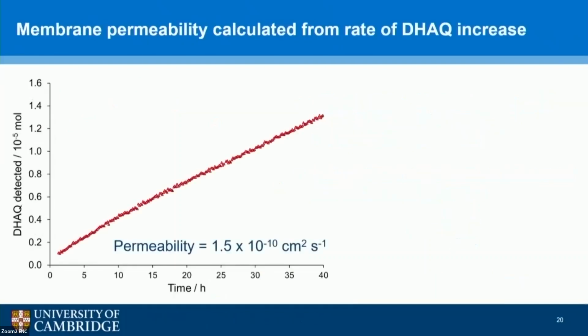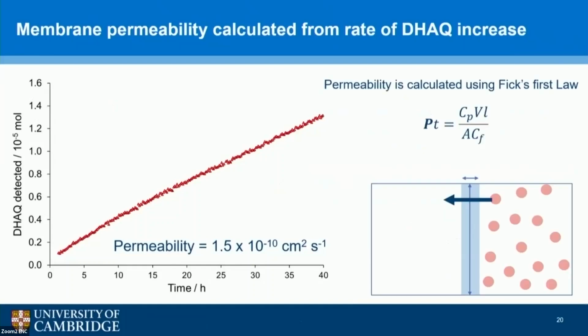So basically from this, we can obtain quantitative data about the increase in concentration of quinone over time in the other side of the cell. And from this, using Fick's law, we can just look at the increase in concentration of quinone. It's basically a permeability that's normalized by the area of the membrane and the membrane thickness. And we just use this to get a permeability value, which is a useful metric to compare the performance of this electrolyte with different systems.